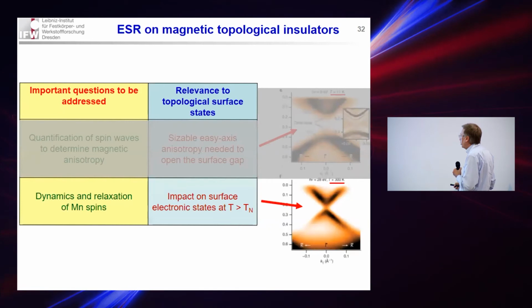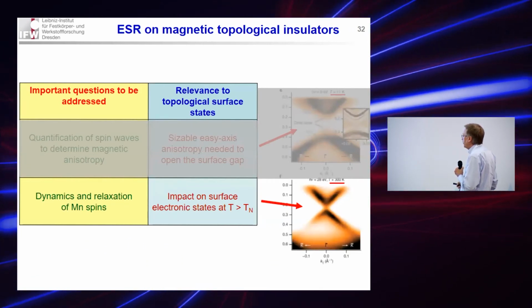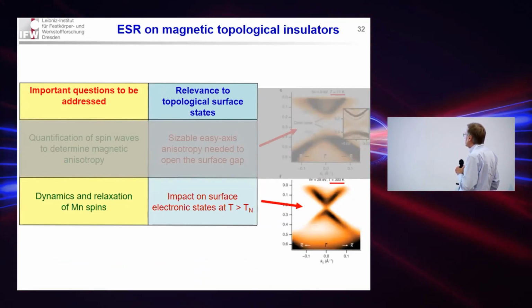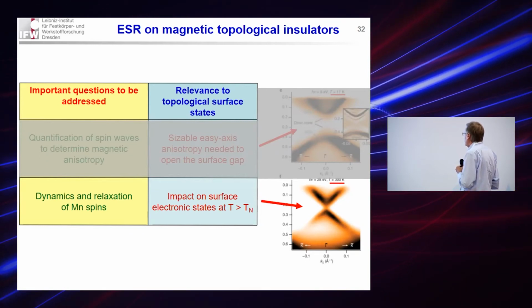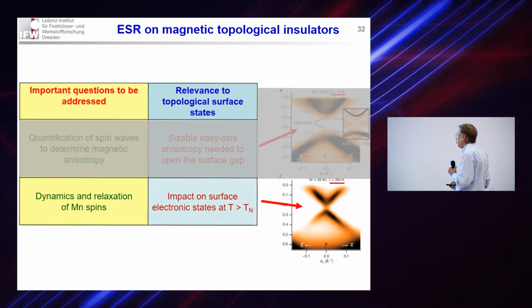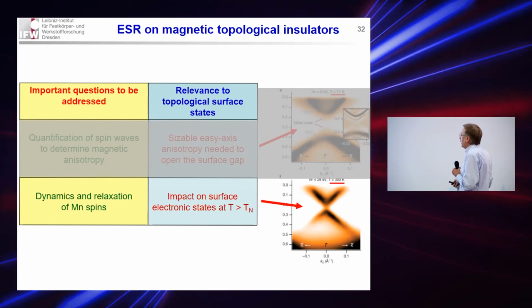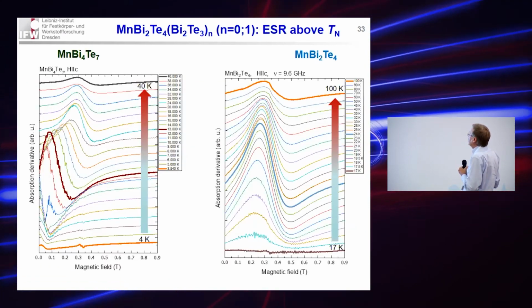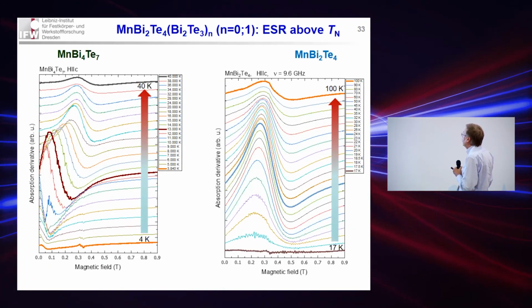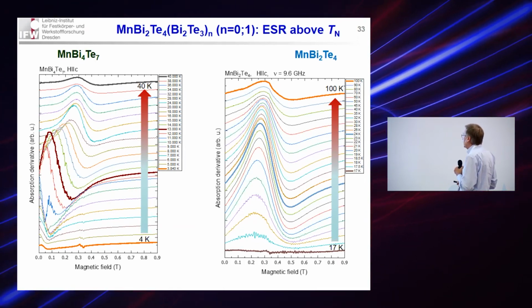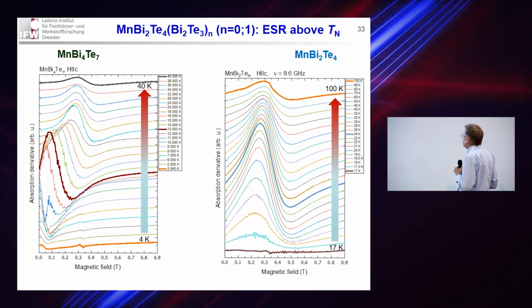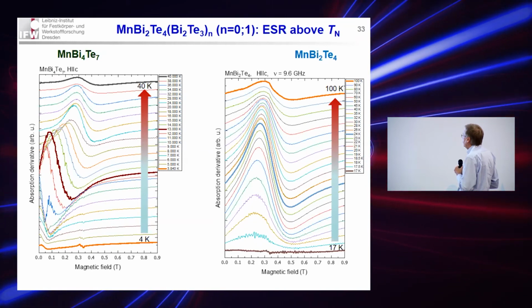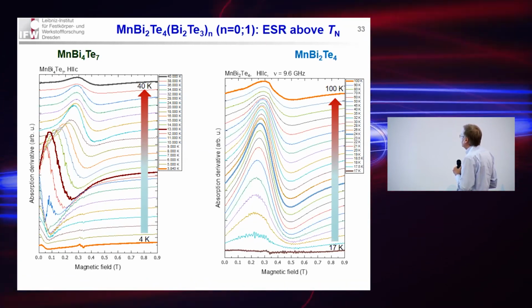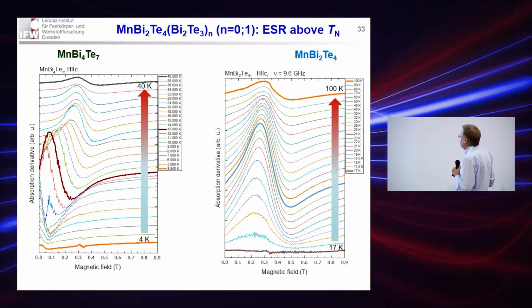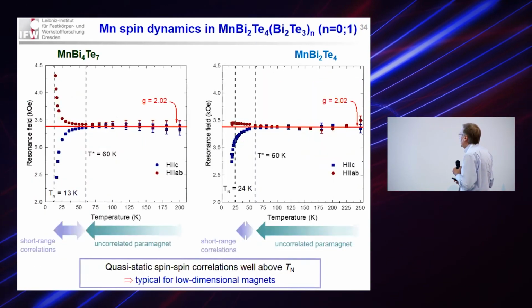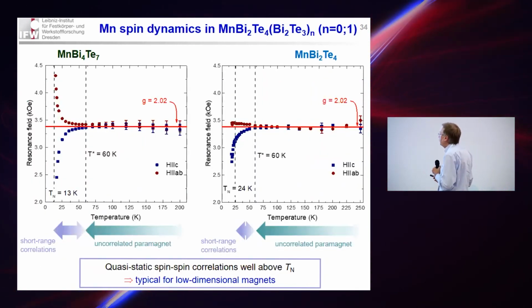And now I will shortly comment on our results on the dynamics and relaxation of manganese spins above the ordering temperature in the paramagnetic state, where we also came to very interesting conclusions. Now, we measured electron spin resonance in both materials above ordering temperature, and in this case this is the derivative of the absorption signal. So you see the line shifts a bit, then it broadens, and the resonant field has the following temperature dependence.